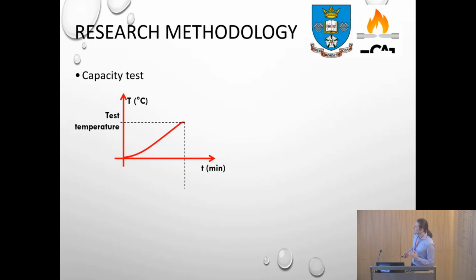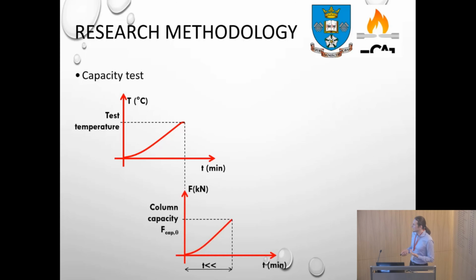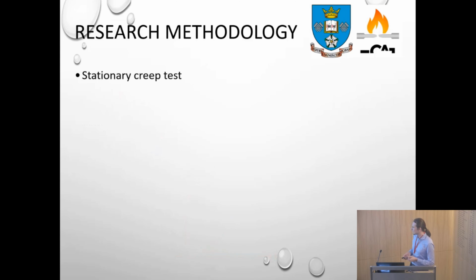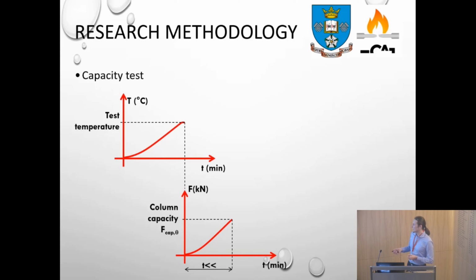Basically what we did with columns, we did a classical capacity test. We established the test temperature and did the capacity test with a very low time interval of testing, as much as possible. And this is our capacity of the column. We also applied the vertical force during the tests in order to simulate the geometrical imperfections.